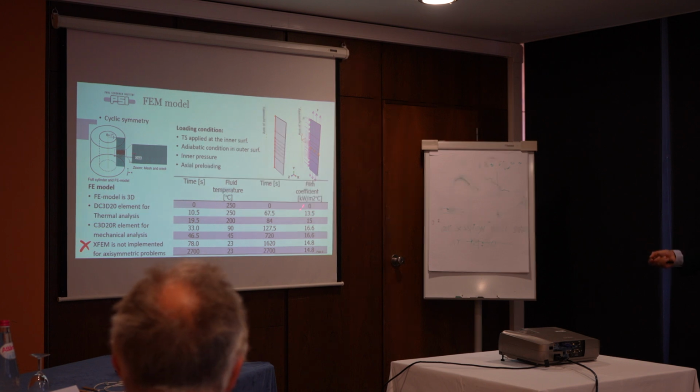The loading conditions are described here. We applied a thermal shock on the inner surface as indicated in this plot, with adiabatic conditions on the outer surface. The thermal shock follows this table. Basically we have the temperature of the fluid and the heat transfer coefficients, and the inner pressure that I said before is 5 megapascals, and an axial preloading. Additionally, we include boundary conditions in the middle plane in order to avoid rigid body motion.